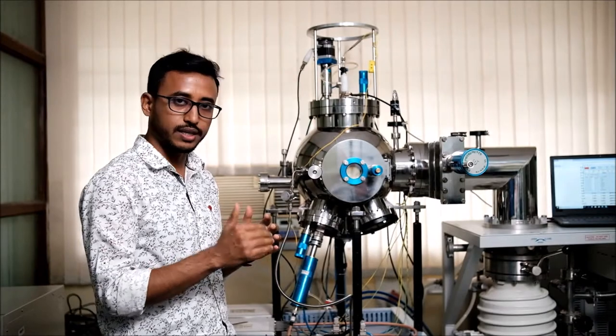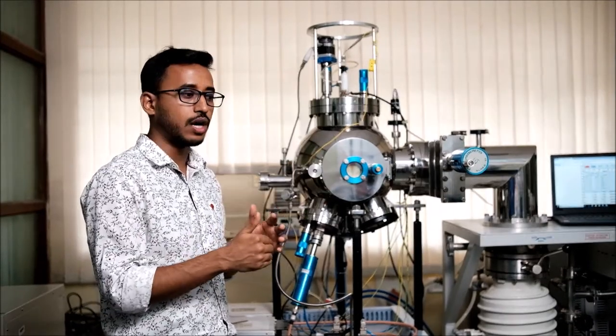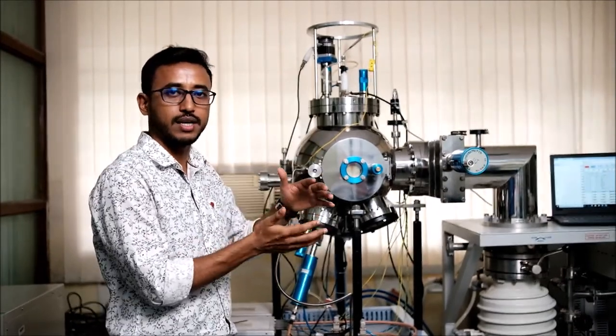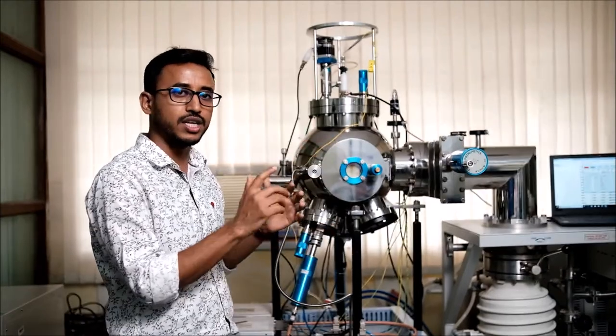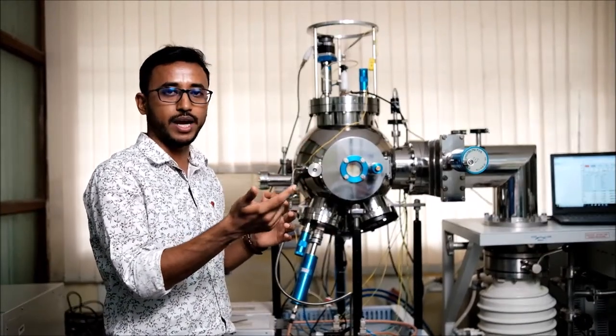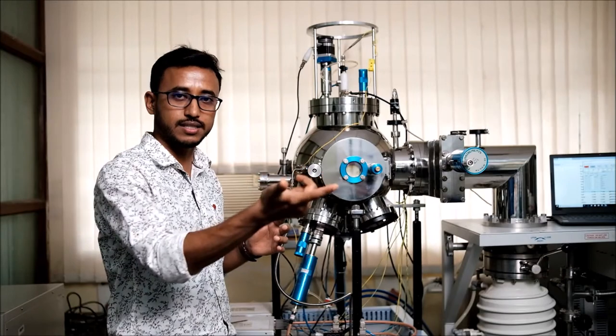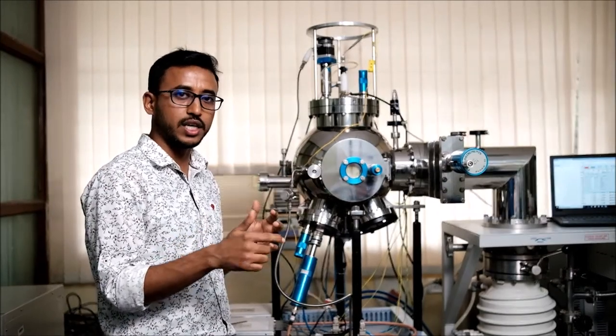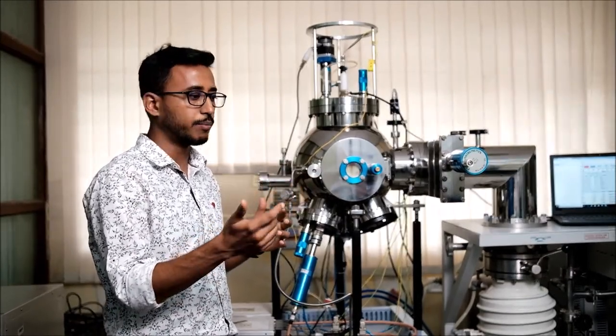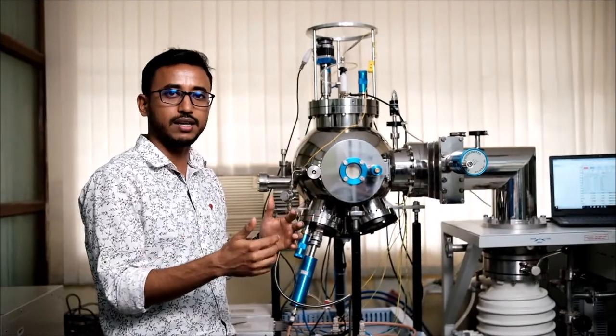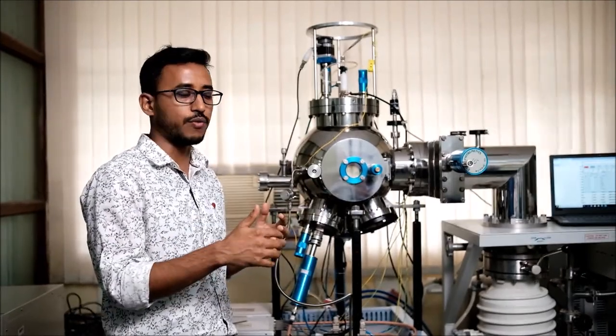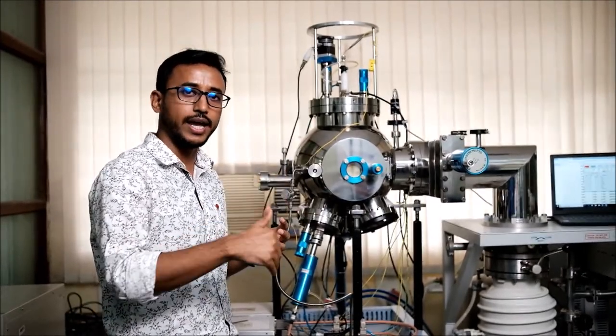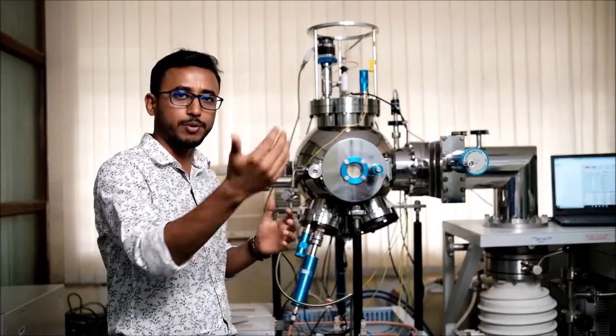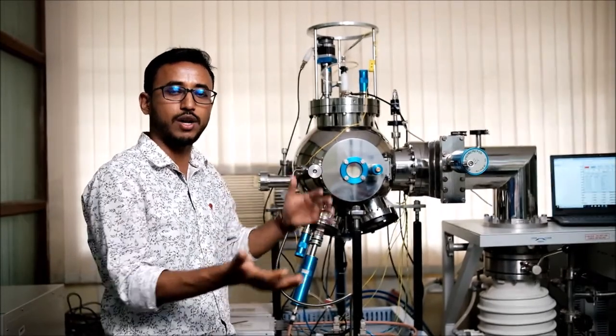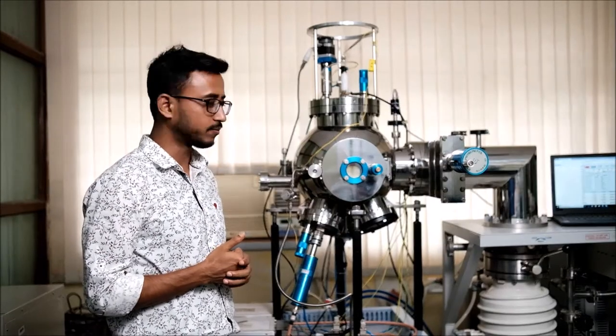So as we increase the pressure, more argon ions are present inside the chamber. This increases the plasma, and thus the deposition rate increases. And if we keep on increasing the working pressure, because more ions are there, more scattering happens. So after a certain amount of pressure, again the deposition rate goes down. So we have to take care of these parameters by optimizing them.